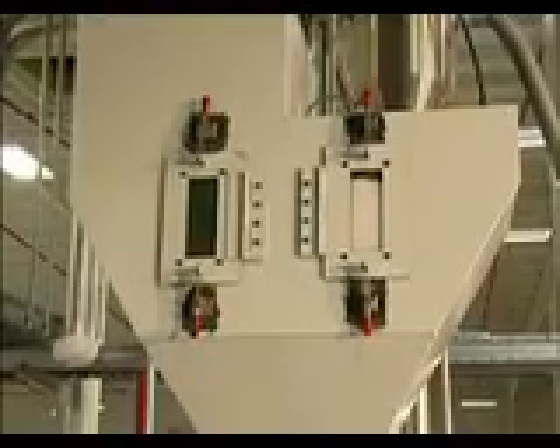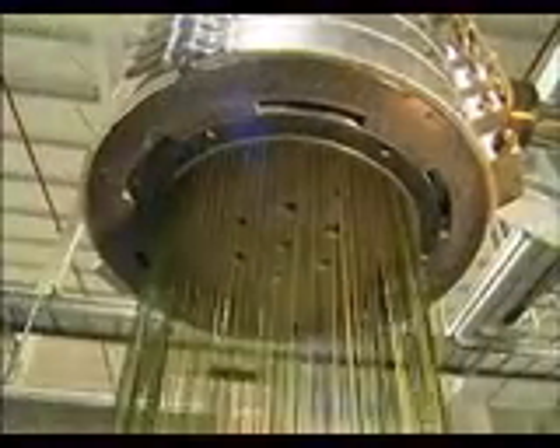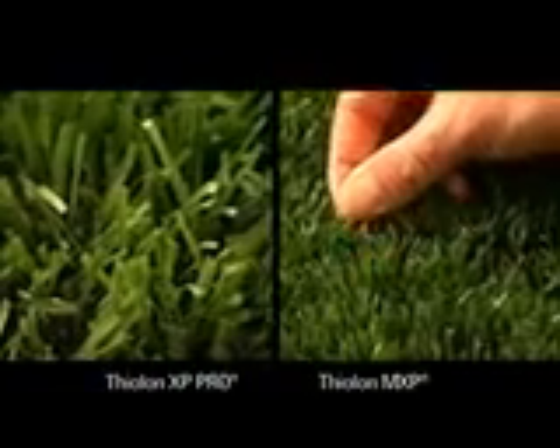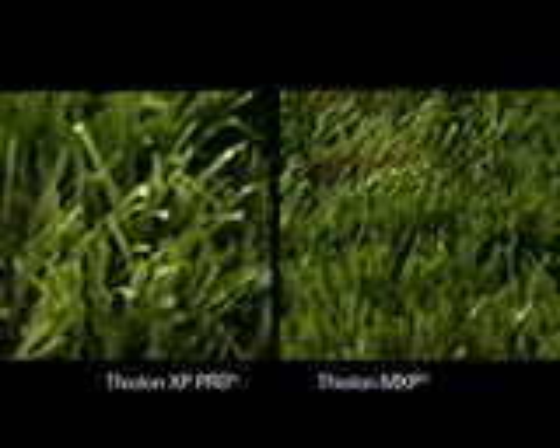After the compounded mix of pellets and additives has been carefully determined, the resin mixture is then sent to the extrusion line and into a blending hopper. The extruder heats the resin compound to its melting point, then pushes it out of a die or opening, much like a pasta maker. The molten polymer exits the die in a sheet form as one of our fibrillated fiber products like Thiolon XP Pro, or as a single-strand monofilament fiber product like Thiolon MXP. Both the fibrillated and monofilament polyethylene fibers have performance characteristics ideal for use in a wide range of sport and landscape applications.